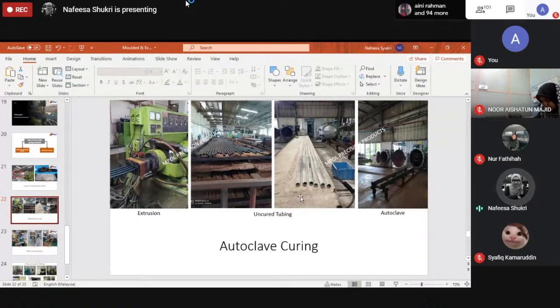We don't want it to coagulate with each other, because coagulated powder will affect the surface of the end rubber tubing. So it is very important to monitor the powder, to add in the powder, and also to handle the uncured rubber tubing. So this is a very important process for autoclave before it goes into the autoclave.